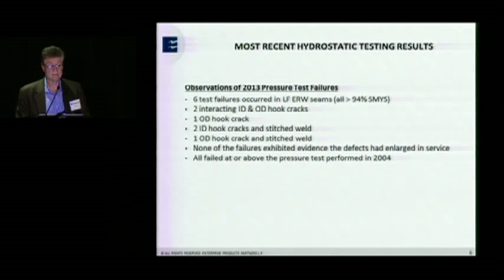And then the last test round, in 2013, we had 6 test failures of the seam, all in the seams again. This time all the pressures were above 94% SMYS. So our testing philosophy was once again above 90%, less than 100%. And you can see we had hook cracks and interaction of hook cracks and stitch welds. Based on sending it to the lab and getting the lab results back, once again, no observed fatigue growth on any of these.